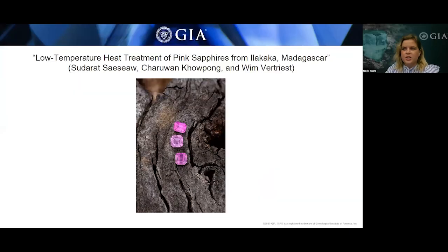Hi. So heat treatment has been used to improve the color and/or clarity of corundum for more than 1,000 years. Various parameters such as temperature, heating and cooling time, and an oxidizing or reducing atmosphere will affect the final color. Now, the border between high temperature and low temperature heat treatment is roughly 1200 to 1350 degrees Celsius. Heating at such high temperature will damage most inclusions in corundum and is often detectable by trained gemologists.